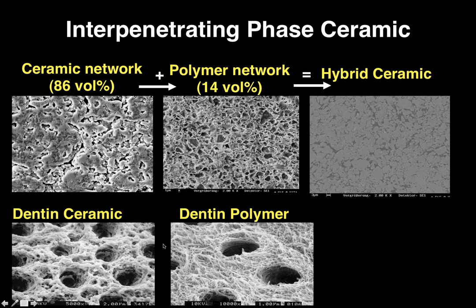Part of the initial thought process was to try to mimic natural tooth structure. And if you look at a dentin material, it's an interpenetrating phase structure, a double network hybrid of a ceramic, which is hydroxyapatite, with a polymer, which is collagen. And years ago when I was working at Harvard as a student, we also had to do a research project as a dental student. Because we're Harvard, we have to do research no matter what. I was looking at bonding studies, and really most of the bond that occurs between the dentin bonding agents is with the collagen and not necessarily with the ceramic. So this is an interesting first iteration of what a natural tooth structure would be.